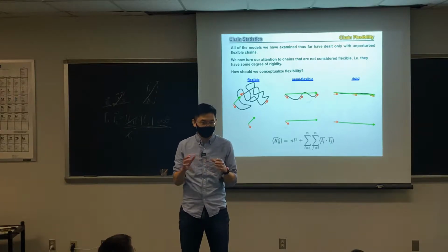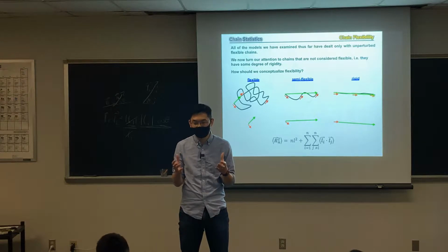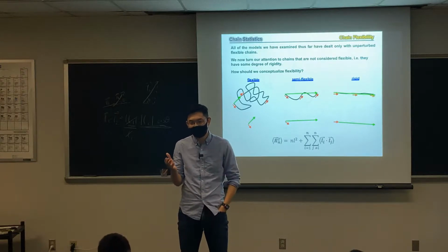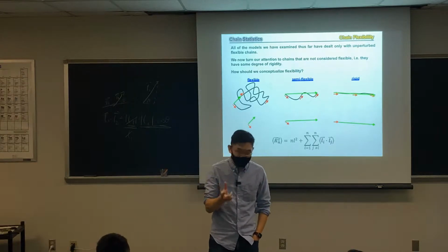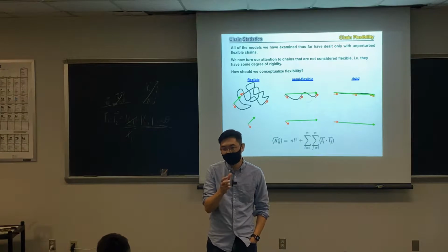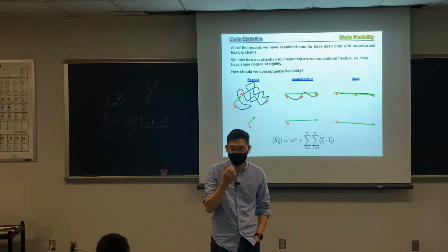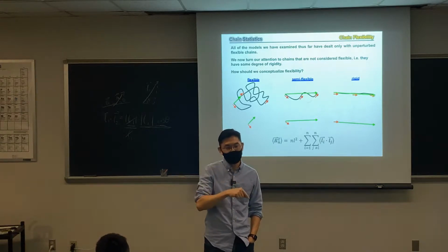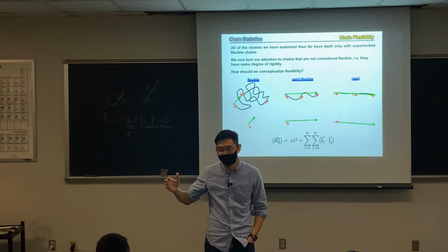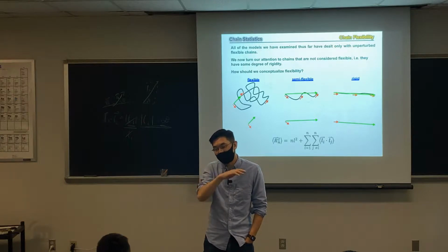But there is one caveat. When C infinity is small, it starts to lose its ability to capture, because C infinity of 2 divided by 2 equals just 1 LP. It doesn't make full sense. But if you think about polystyrene, the characteristic ratio is roughly about 7. So you use 7 divided by 2 and multiply by L. That's roughly LP. That means after 3 or 4 repeating units, it already loses its directionality.